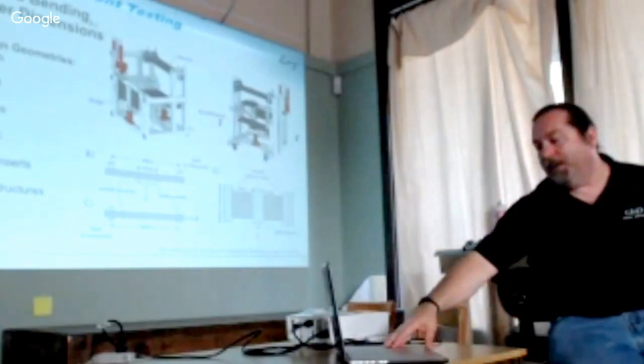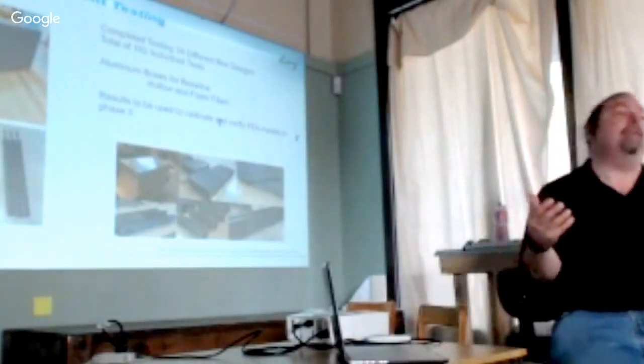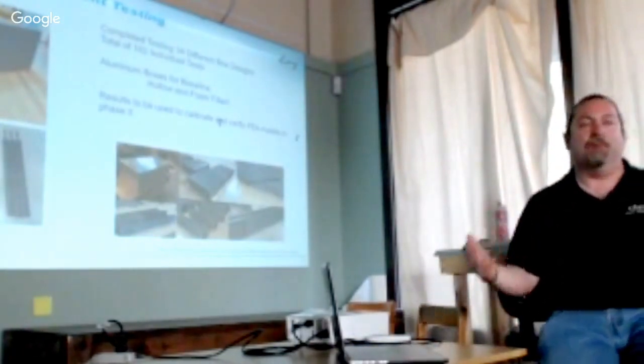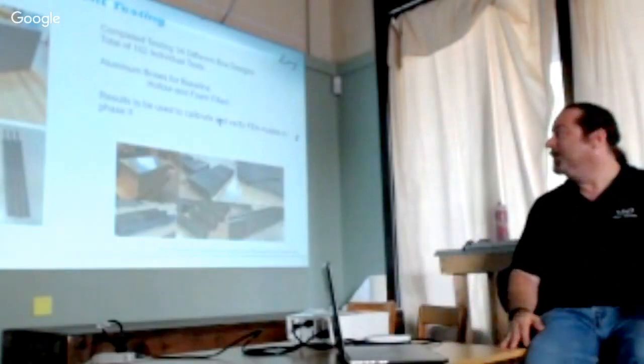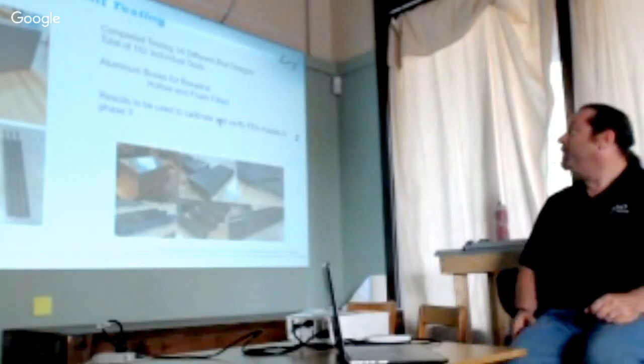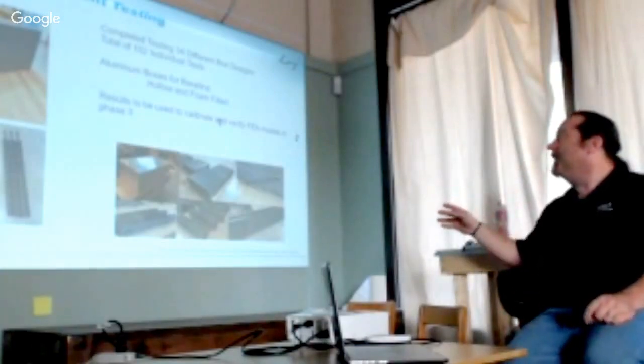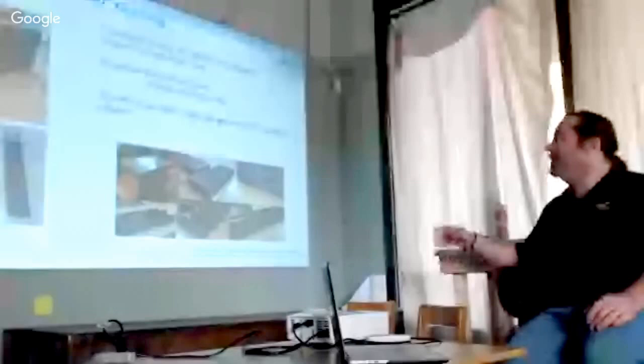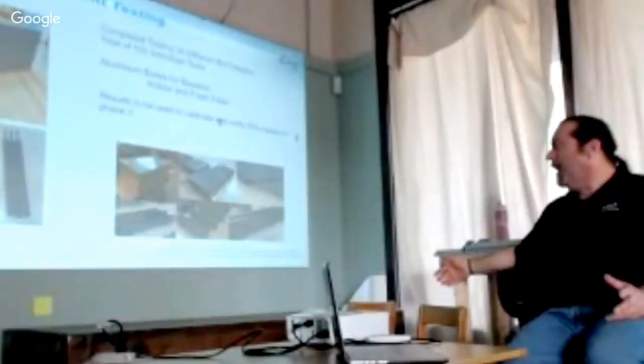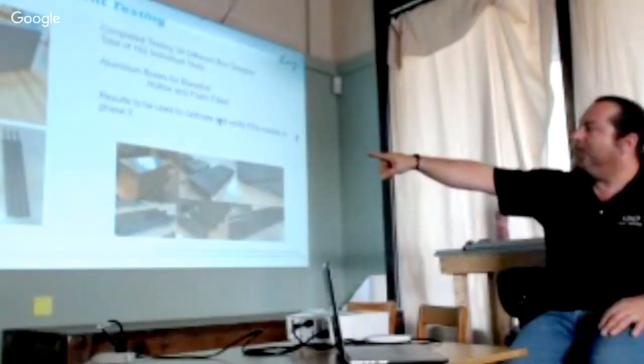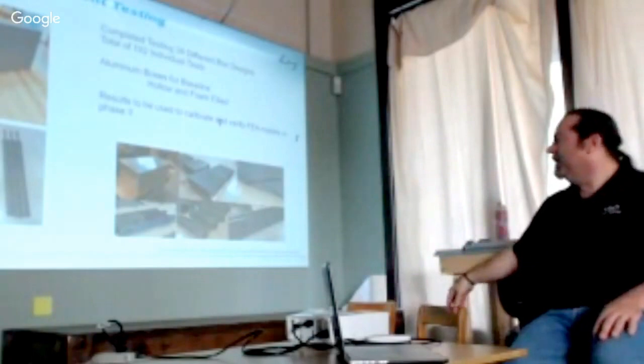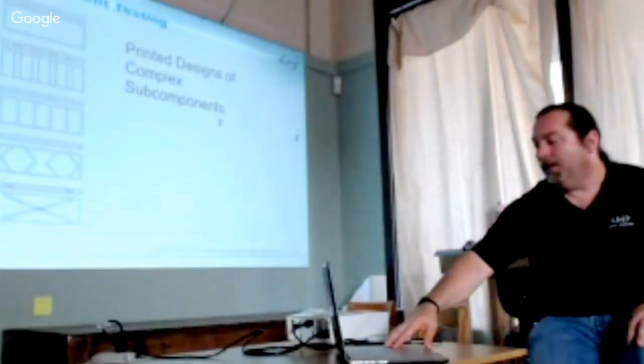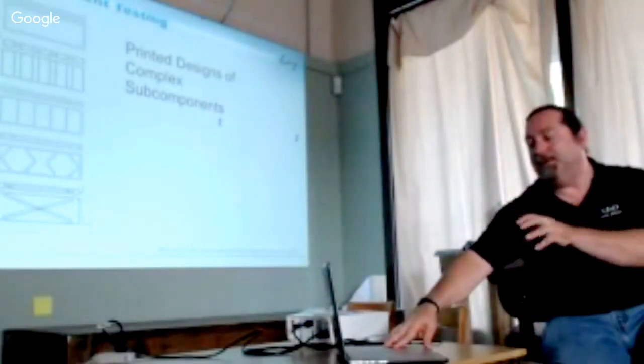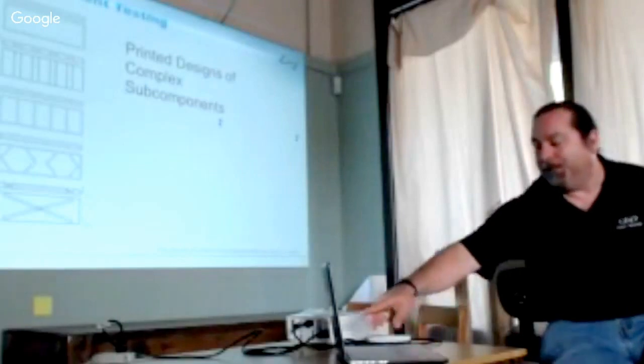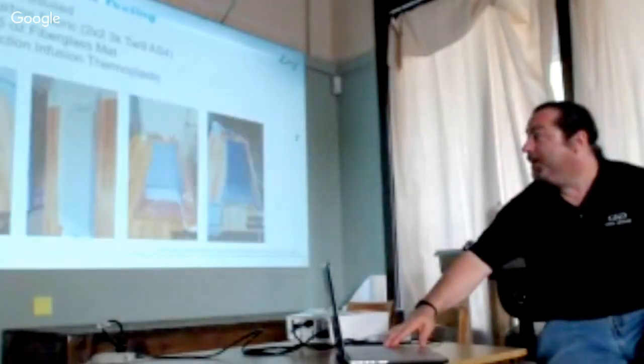That was another way to improve. We really want to communicate to the designers the different possibilities for designing structures using 3D printing, and this was part of that. We completed about 34 different box designs for 102 individual tests. We used aluminum boxes as a baseline, and we also had some aluminum that was foam filled and just hollow welded. These show the different infill patterns, again the manual infill patterns. These are hidden in the box, but this chevron type box, I'll show you this. I've got some details of that.